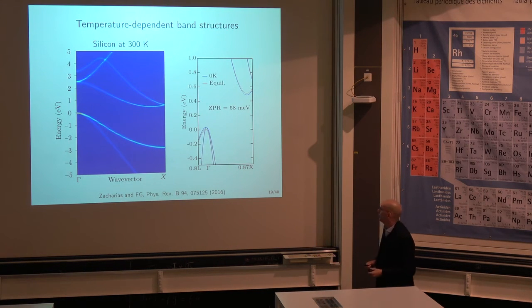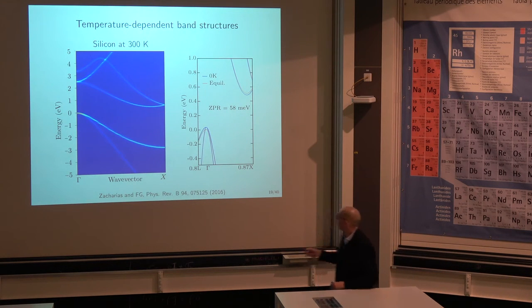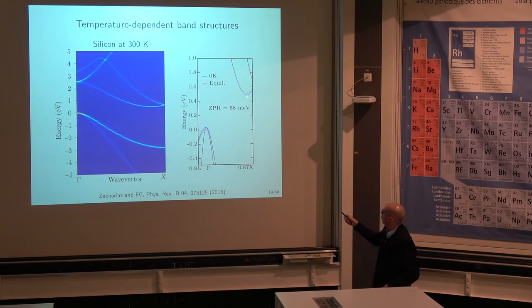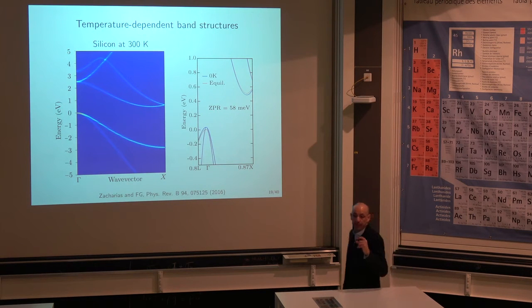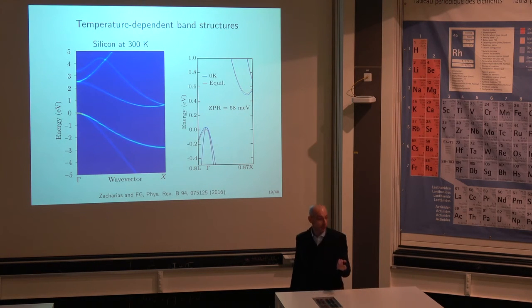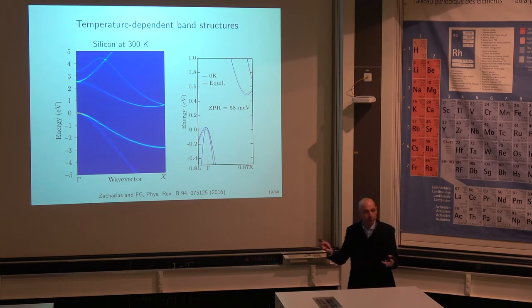In this case, I'm just showing you the difference between a calculation at 0 Kelvin, DFT, and a calculation again at 0 Kelvin, but including quantum nuclear effects. So what you see is that the incorporation of quantum nuclear effects decreases the conduction band bottom, increases the valence band top, and as a result, the band gap decreases by about 60 millivolts. Okay? Clearly, 60 millivolts is a small number in this case. So you say, why bother doing this?